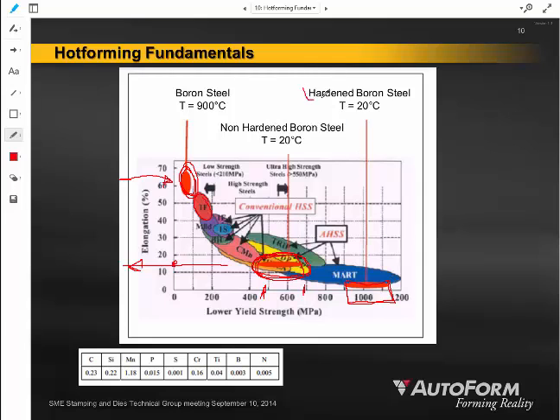However, this boron steel, when you heat it and cool it in this manner, you can end up with a material that is up to 50% stronger than the material was when we bought it from the mill. So we're adding value to the material in two different ways when we're doing this hot stamping. We're adding value by making it take on a new shape, and we're adding value by making the material stronger than it was when we first bought it. So that's a double dip as far as value add manufacturing processes. It's stronger and it's in the product shape.